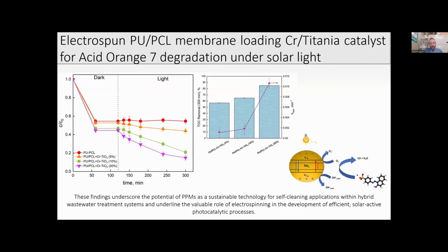Even in this case, we varied several kinds of process parameters. The process seems to be favored in acidic condition, room temperature, and with a 20% loading of chromium-doped titania. This kind of material seems to be able to more or less fully remove the acid orange 7, photodegrade actually this contaminant from water solution. So this data further prove the potential of this membrane as a sustainable technology to photodegrade this contaminant from wastewaters and to be used for self-cleaning solutions.